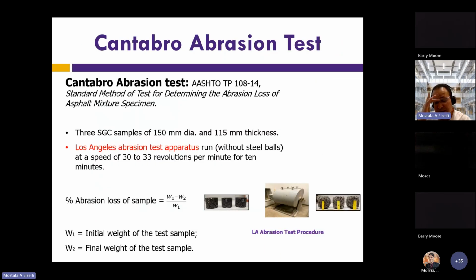So the Cantabro abrasion test is a test that was highly recommended for OGFC because it is very prone to raveling, and it really subjects the mix to a significant effort to cause raveling, and it provides a very clear assessment of this failure mechanism. So the way it's conducted is that you place your specimen in the LA abrasion drum, which is shown here, and you place it without the steel balls. So that's a small modification. And then you conduct the test for 10 minutes, and you measure how much aggregate or how much mix loss you had at the end of the test. And again, this test is a very important test to assess OGFC mix.